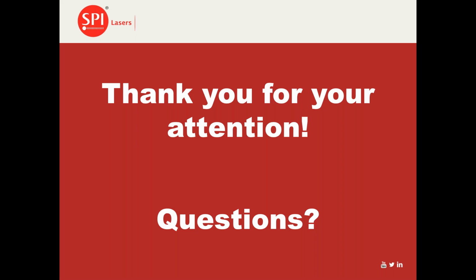Can CW and QCW lasers also be used for cleaning? So the answer to that is yes, in some circumstances. However, just bear in mind that they clearly won't have the levels of controllability in the characteristics that I've discussed throughout this webinar in terms of peak power, in terms of pulse duration, in terms of pulse energy. That will enable you to deliver the energy to the surface with the control that a nanosecond pulse laser would provide. You can use CW and QCW in some applications, but if you're not careful, because of that lack of control in the energy and power to the surface, you can end up with burning and charring rather than clean removal of the surface layers.